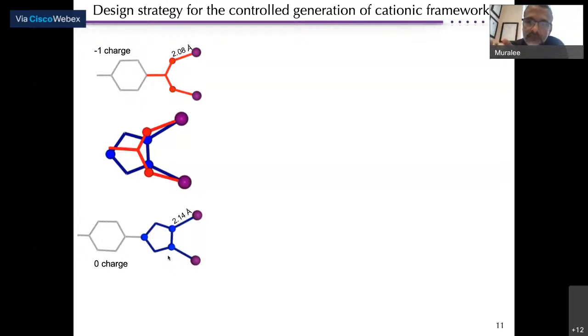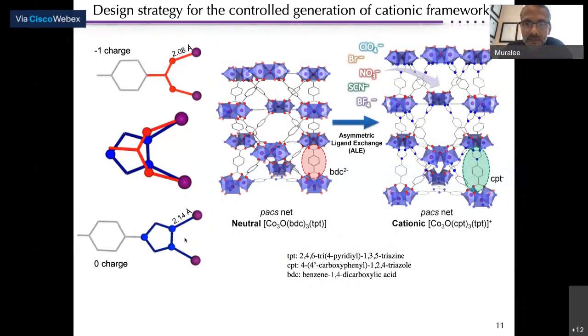So what if we take a framework that is made with dicarboxylate or any carboxylate and replace it with our asymmetrical linker? Therefore, we will be able to change the whole charge of the framework. So instead of a neutral system, we can take a neutral system and make a charged framework. You might wonder, why do we want a charged framework? Then you can trap highly toxic anions, for example, if you make a cationic framework.